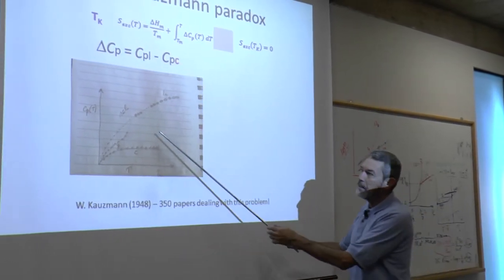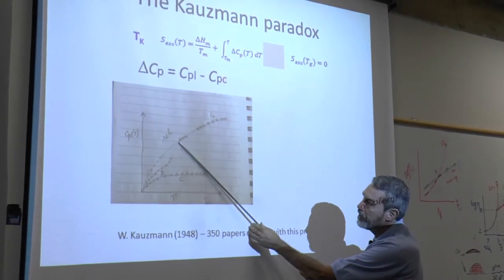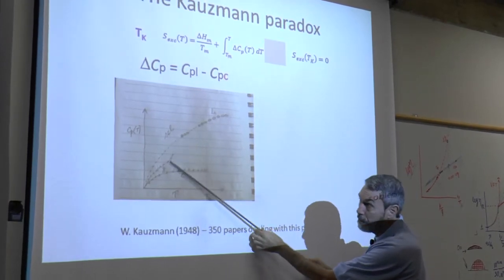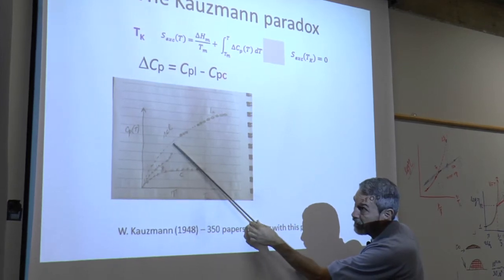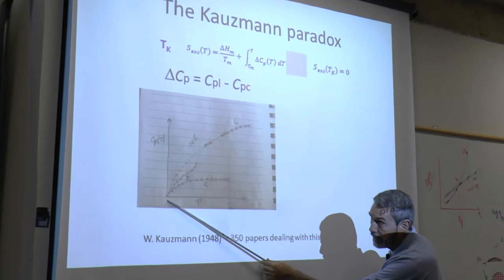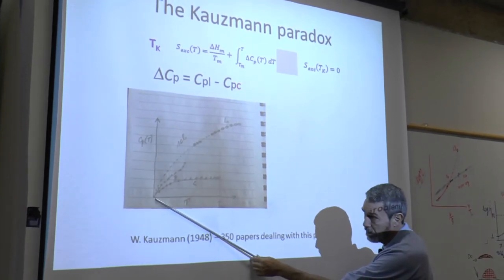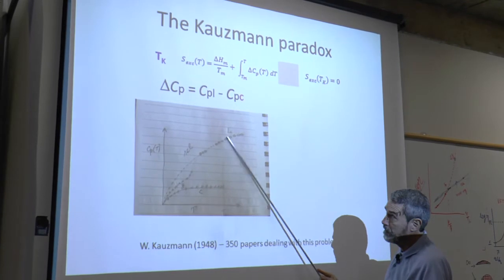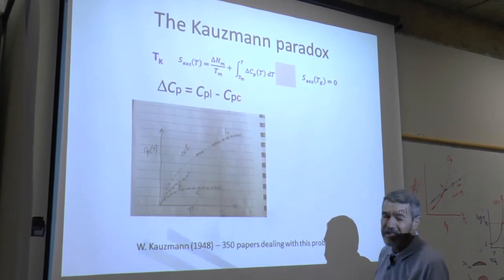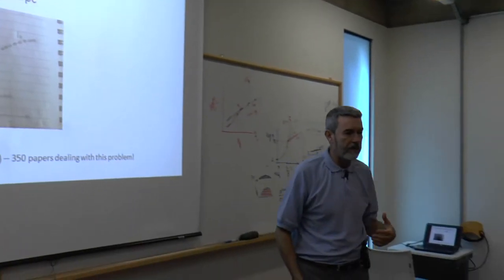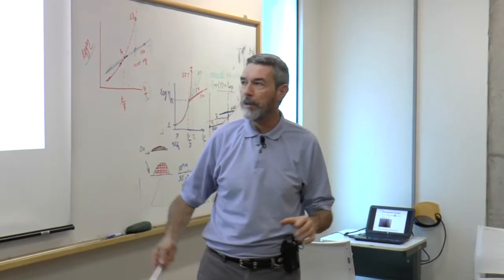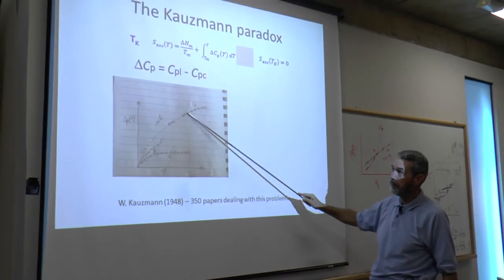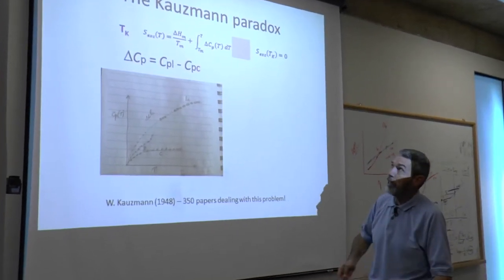The only problem is that there is no data below the Tg. So there is data for the liquid above Tg, but of course there is no data below Tg because then we have a glass. So you need to fit this part here. You know that the Cp at 0 Kelvin is 0. So you have this data point here that you force in your fitting, and you have all this data here. You have to fit some equation. And there is no good theoretical model for that, unfortunately. There are a few expressions, but I'll leave this open to you. You have to fit some smooth curve, a smooth curve from here to here for the exercise.